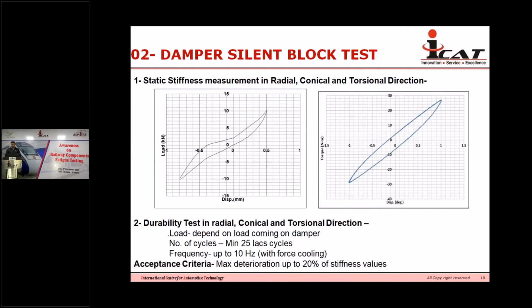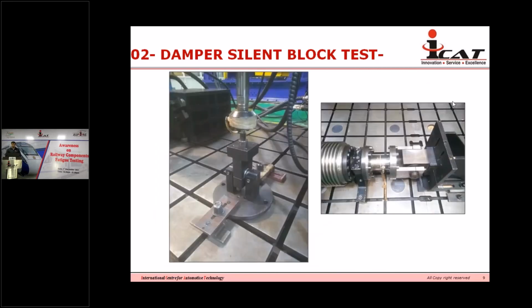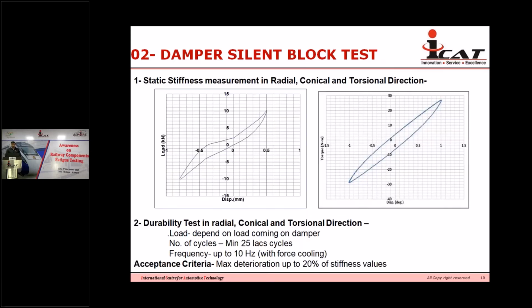We give plus minus 1 degree or plus minus 2 degree displacement through our rotary actuator. This is our rotary actuator, servo hydraulic. And this is one of our load cells, a torque cell, and the rotary actuator has a rotational displacement sensor, and it gives the value in terms of degrees. We give an amplitude of plus minus 1 degree, and we check how much torque is coming. So torque divided by that displacement, we calculate at 1 degree. This gives us the characteristic value of the performance test of these silent blocks.